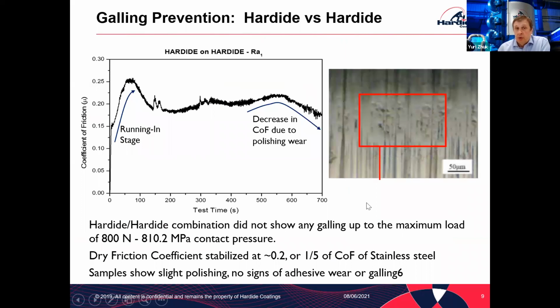The coating has very good anti-galling properties. So when tested dry, Hardide-coated component against Hardide-coated component maintain a friction coefficient of 0.2, which is about one fifth of a typical stainless steel against stainless steel. And the samples didn't gall even under higher loads, representing about 800 megapascals contact pressure.